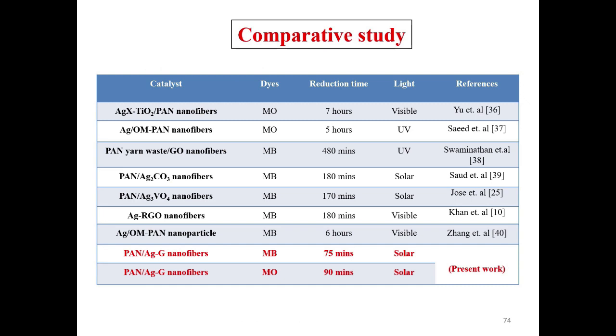When we compare this study with the other nanofibers, we observe that PAN/Ag-G nanofiber in case of methylene blue at 75 minutes in presence of solar light shows very effective degradation. Degradation is taking place in 75 minutes only. PAN/Ag-G nanofiber for methyl orange takes 90 minutes. If we compare with the others, they take 6 hours, 180, 170, 180, 480 minutes, 5 hours, 7 hours and so on. Our work seems to be very capable